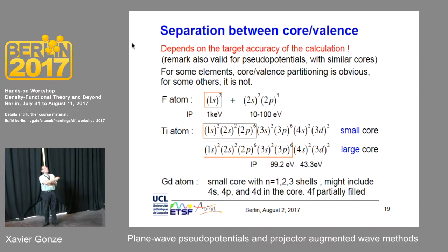This will actually be fine for the titanium metal, because in the metal the 4 electrons will roughly occupy these 4s and 3d states. But if you take barium titanate with the oxygen pumping the electrons from titanium, here we will have somehow a 4s 0, 3d 0 state, and the 3p and 3s orbitals will be rearranged. You cannot get correctly barium titanate by using this separation.